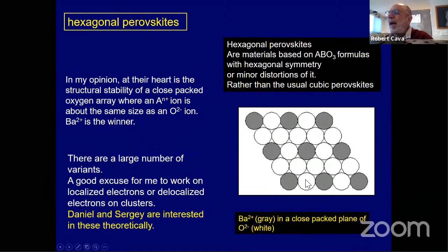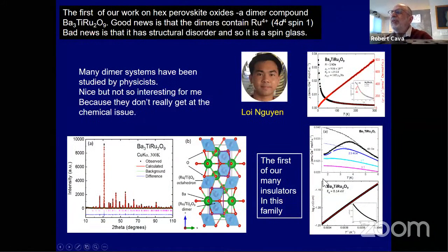So if you take the closest packing of spheres, which is an extremely stable configuration, and you mix barium in with oxygen, so here's barium 2+ shown in gray, and oxygen 2- shown in white, when you mix them together, they can form an ordered lattice. And the ordered lattice has a basic hexagonal shape, which is this motif right here. So this can give rise to all sorts of things. And this is my student who was working on these, Loi Nguyen. Again, we do high resolution diffraction on these things.